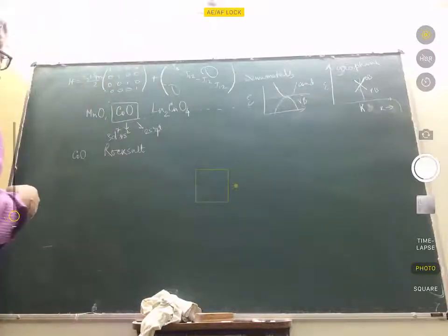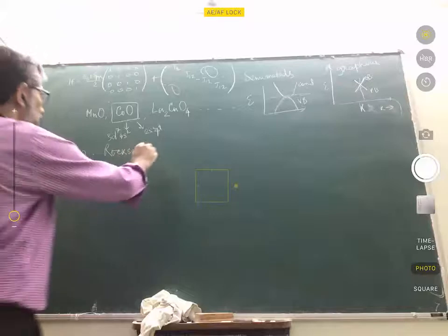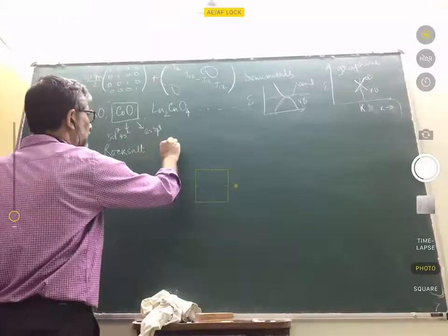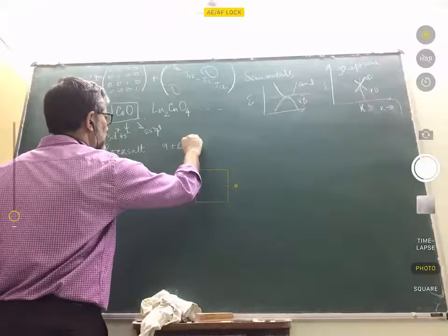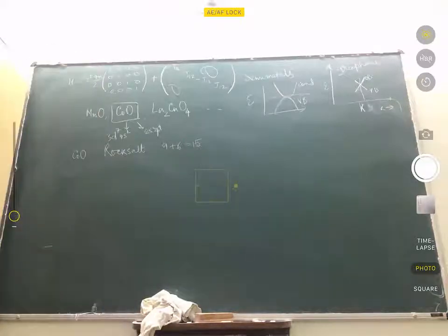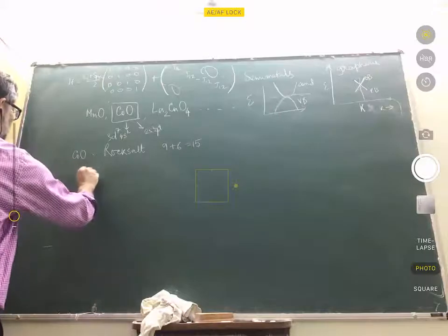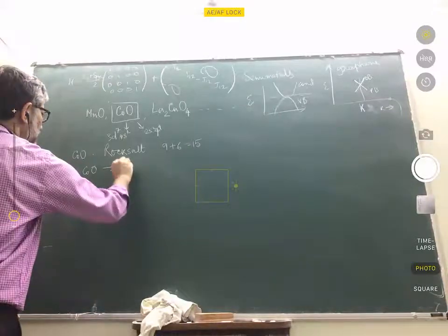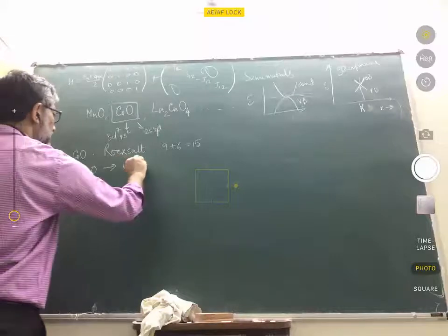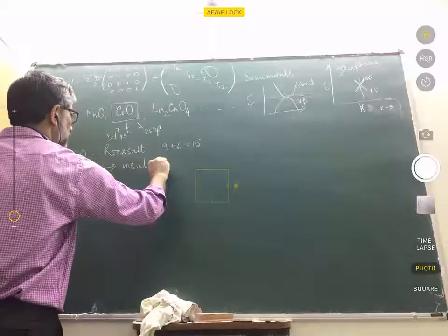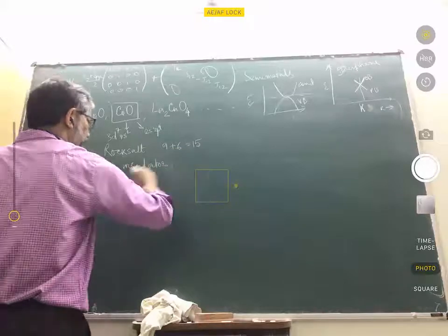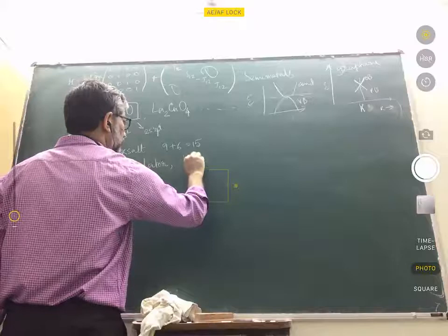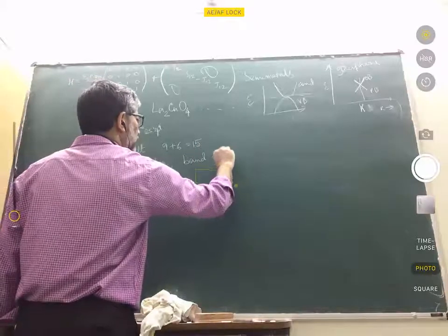So then I can calculate the number of valence electrons in a unit cell. It will be 9 plus 6, which is 15, an odd number. So according to band theory, this should be a metal. And that completely throws our understanding out of the window, because cobalt oxide is an insulator with a band gap of something close to 3 eV, which is a pretty large gap.